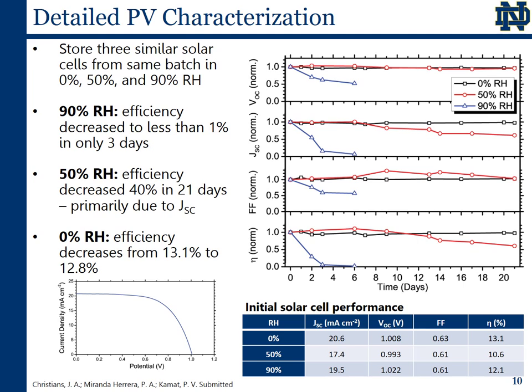On the other hand, solar cells which are stored in dry conditions show promising stability with very little deterioration over the course of this 3-week experiment, although it should be noted that these solar cells were stored in the dark between trials and were not under continuous illumination, which has been shown to speed the degradation process.